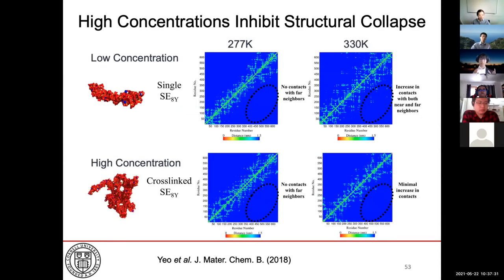And therefore, these intermolecular interactions actually inhibit the remodeling into more compact structures. And this is observable, again, from the contact maps, where there's a minimal increase in the number of contacts with neighbors that are much further away in cross-linked clusters, in contrast to the very large increase in contacts for a single molecule above the transition temperature.